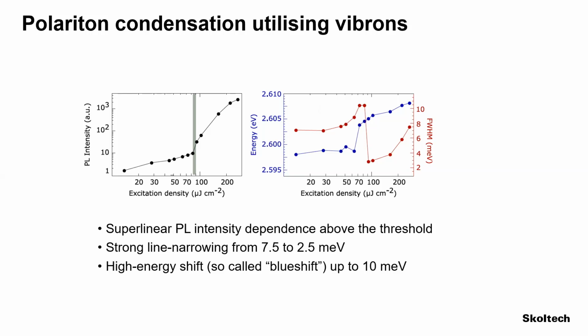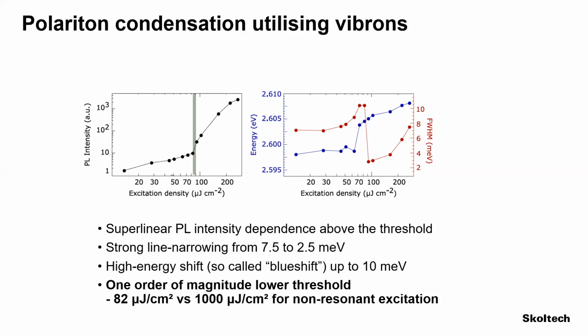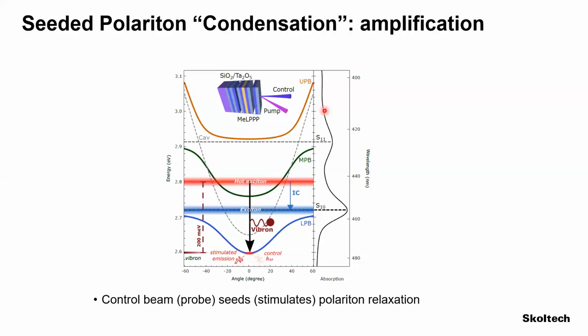a bit more than 10, one order of magnitude lower threshold, by allowing for polaritons to jump to the ground state through the emission of one vibron. Okay, so you accelerate very much the relaxation of energy. Now, to do that, first of all, you need to pump resonantly a hot exciton reservoir, which is exactly one vibron above the ground polariton state. By doing this, we create here a coherent state, a polariton Bose-Einstein condensation, which was at lower threshold. Polaritons didn't have to come across the dispersion, just through the emission of a vibron they were coming here.